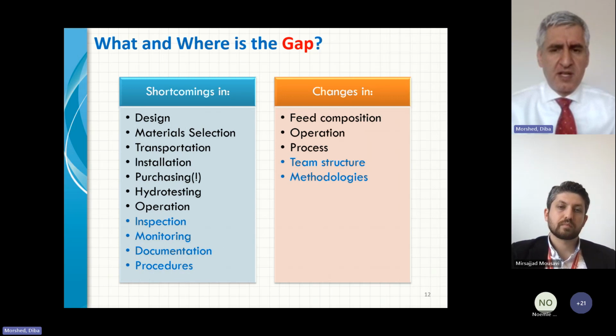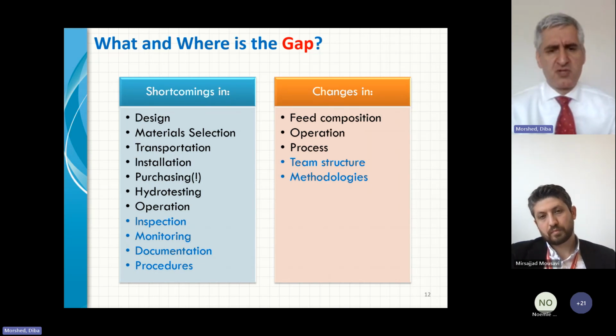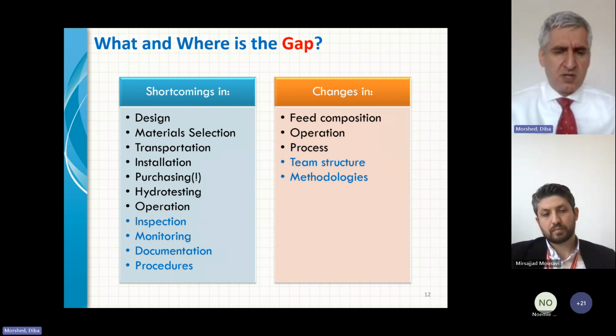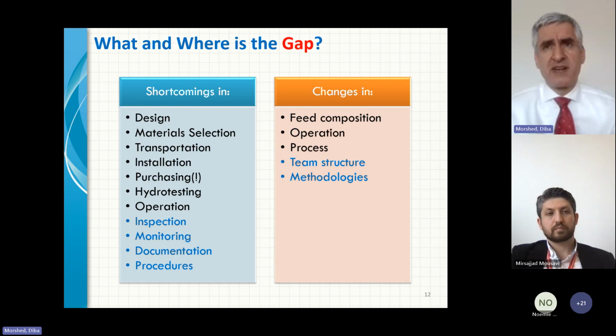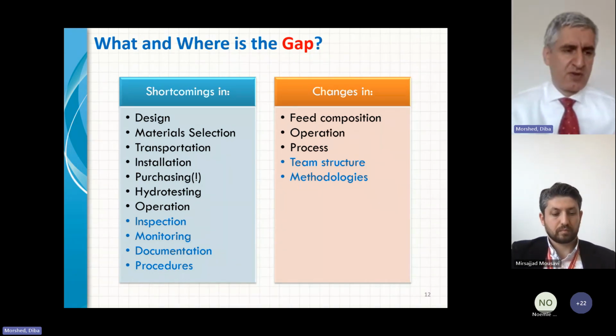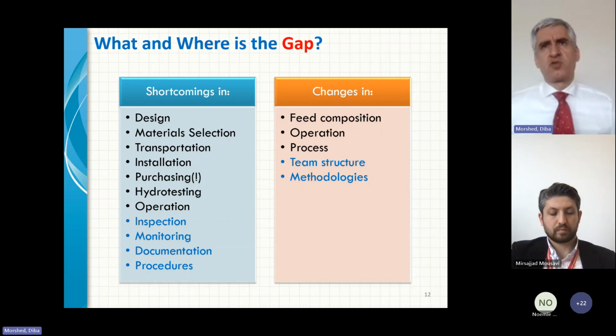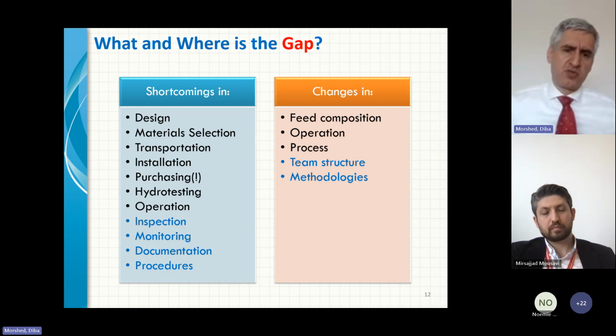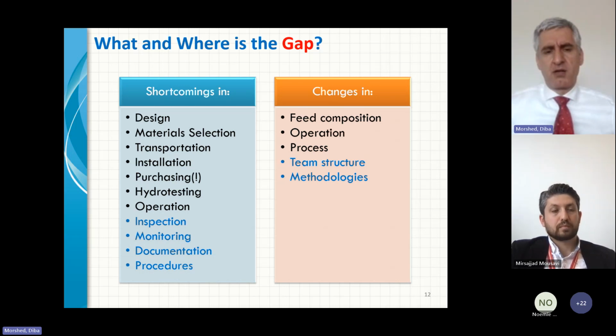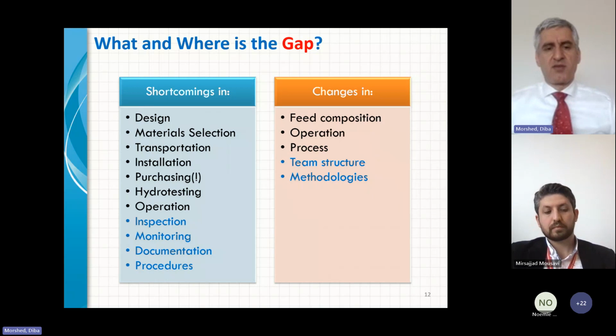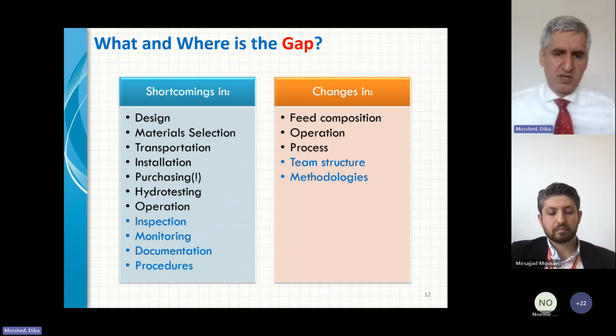I have used two different ink colors here on this slide. Some parameters are written in black, some parameters are written in blue. The blue ones, like inspection, monitoring, documentation, and procedures, are the non-corrosion engineering ones. The inspection parameter is that sometimes, unfortunately, in some projects, we do not carry out any inspections until the first signs of corrosion appear. The same goes with monitoring. They do not install any corrosion rate monitoring system. They do not do any sampling. They don't see any value in that until corrosion failures start appearing, and then they start fitting corrosion rate monitoring equipment into their process systems.